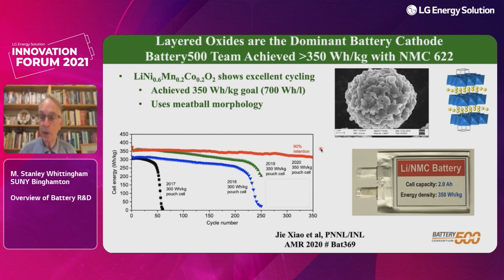And this is a typical cell. They're all about 2 ampere hours. So this is 350 watt hours per kilogram and 700 watt hours per liter. So this is where the Battery 500 project stands now. There's optimism we will get well over 400 and maybe even achieve the 500 goal. But to do that, we've got to use all this lithium in these layered oxides.